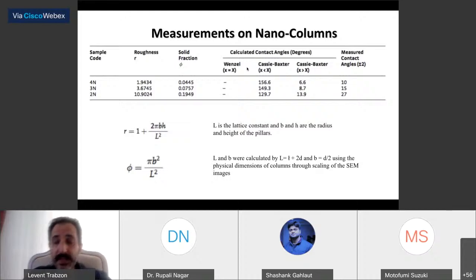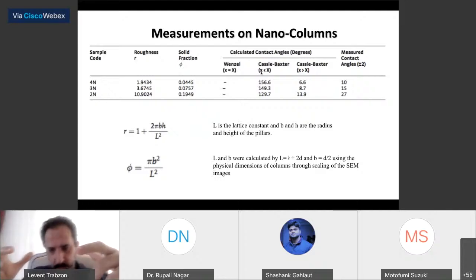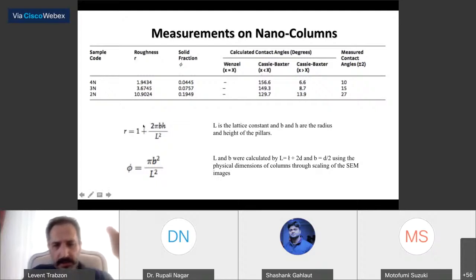But unfortunately, Wenzel cannot be applicable to this, because the roughness is bigger than 1. So we concentrate on the Cassie-Baxter model. In the Cassie-Baxter model, small x corresponds to the drop size, the original drop size you are dropping from the instrument. And big X is the size of the drop when it interacts with the surface. Anyway, the roughness is calculated by the model given in the literature.